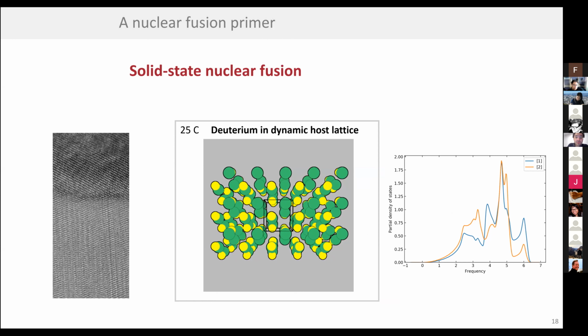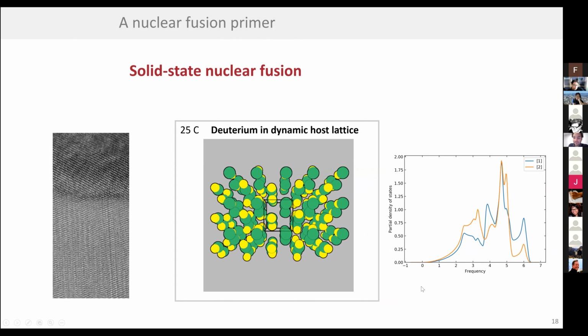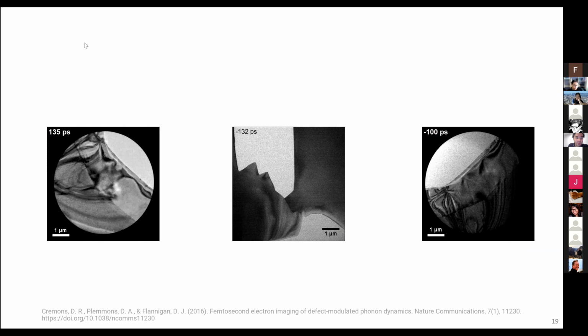And then there are other features, like dynamics. So now we've seen the composition and the structure of these lattices, but there's also dynamics. The lattice can move and vibrate, and people have calculated and measured the frequencies. These are very high frequencies because these are very small structures. And actually, I recently came across some very cool videos where people have extremely high frequency cameras at femtosecond temporal resolution, so that you can see these so-called phonons, these lattice vibrations, in these different lattices. They look like waves that are going through a material.